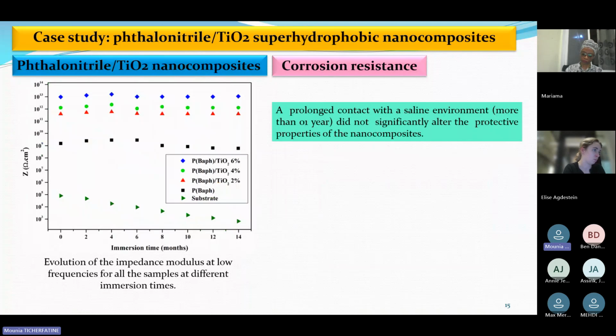Here we have the evolution of the impedance modulus at low frequencies for all the samples at different immersion times. What can be said for sure is that prolonged contact with a saline environment for more than 1 year did not significantly alter the protective properties of the nanocomposite.